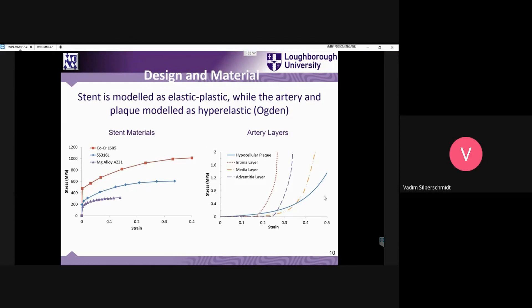As you can imagine, all materials — even including metals and alloys — because they are being used beyond the elastic limit, require complex material behavior models. You can see here all three different metals and their respective stress-strain curves. Biomaterials forming the artery wall and the plaque have a typical soft biological tissue behavior, which can be described with hyperelastic models.